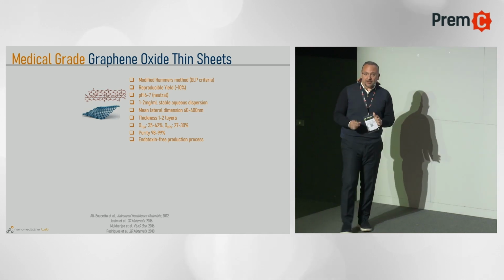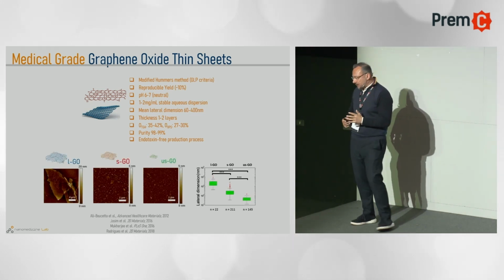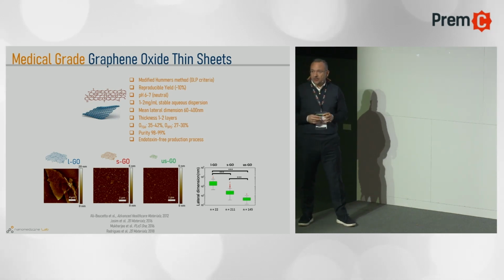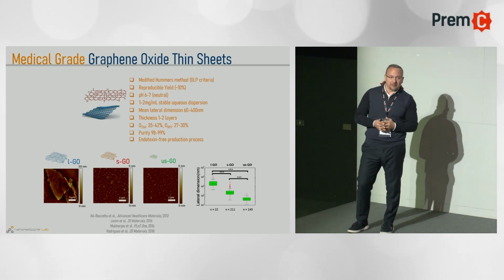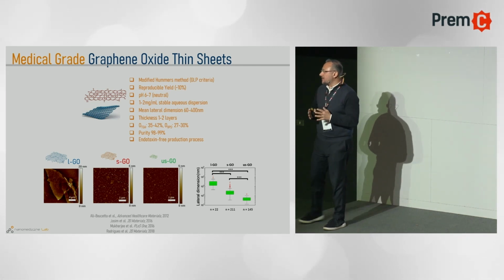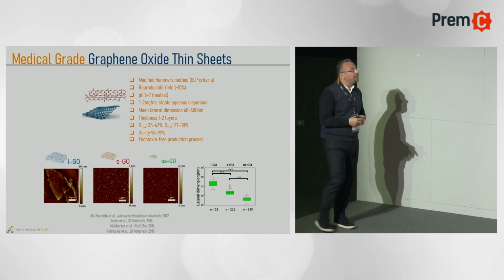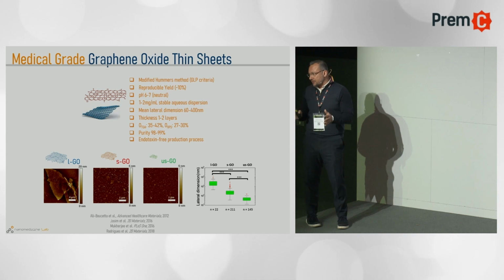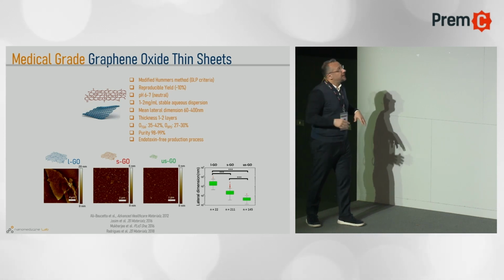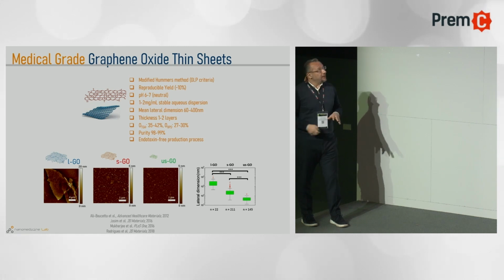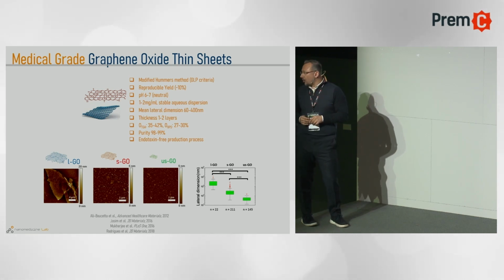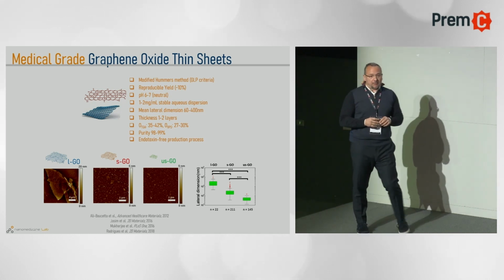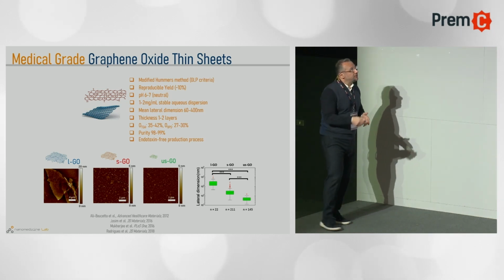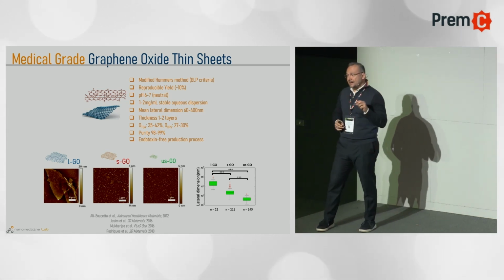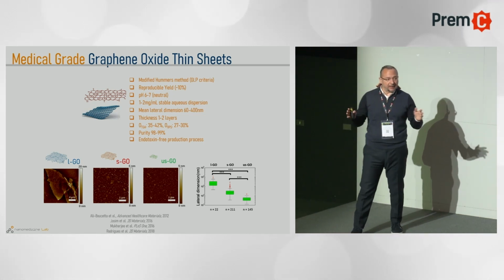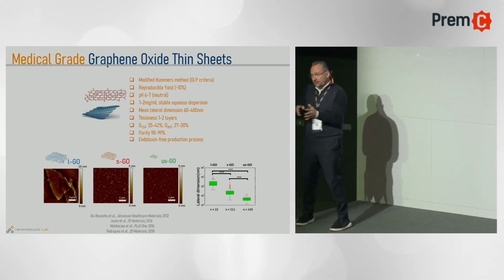The second thing we try to do is vary one parameter only. And this is what we've done here. You can see atomic force microscopy images of the 3 generations and 3 types of graphene oxide materials we established in the lab, and which were the ones that we would push through the clinical pipeline. These we call large graphene oxides, which are in the micron scale. The sheets, the flakes of graphene oxide materials are in the micron scale. What we call small graphene oxides, which are in the low hundreds of nanometers in lateral dimension, and the ultra-small graphene oxides, which are in the dozens of nanometers in lateral dimension.